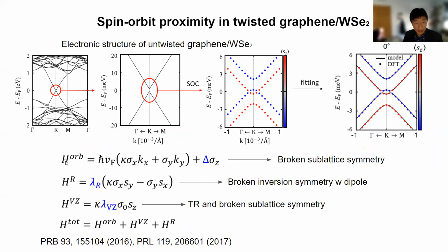One can develop an effective Hamiltonian to describe the graphene. The pristine graphene is described by this Dirac Hamiltonian, but because of the registration of the AB sublattice of graphene with the different atoms of the TMD, one can acquire a net sublattice symmetry breaking, and this is described by this term. Then you also have a broken inversion symmetry with a dipole, which gives you a Rashba-like term, and also a valley-Zeeman term which comes from the broken sublattice symmetry in the presence of time reversal symmetry. This is a Hamiltonian that has been developed in these two papers to describe twisted graphene on TMD.